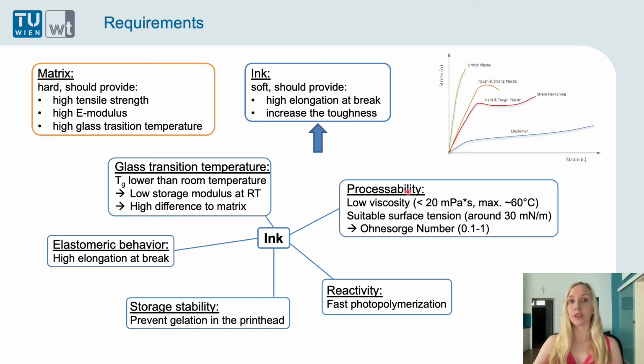Another important point is the processability. Here low viscosity is important because by inkjet printing you need a viscosity that is lower than 20 millipascal seconds, while we can only heat it up to 60 degrees C. And also the surface tension should be suitable according to the manufacturer of the printhead. It should be around 30 millinewton per meter, and out of these parameters you can calculate the Ohnesorge number, which should be between 0.1 and 1 to get a jettable material.